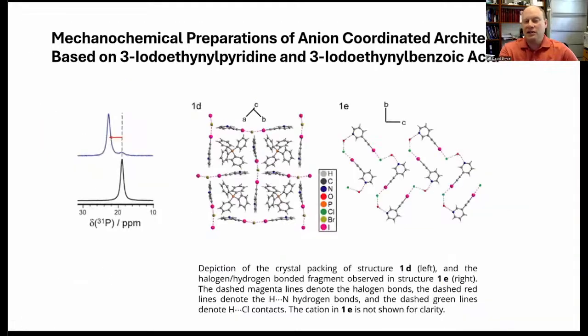And in some cases, in this case, we were able to actually grow some single crystals that match the powder X-ray diffractograms. And a lot of our initial work was trying to see what we could do to reproduce known crystal structures that are available from solution. Of course, we then move on to see what we can do that's new. So I just wanted to highlight the nature of some of these structures. They form very interesting halogen bonded networks.